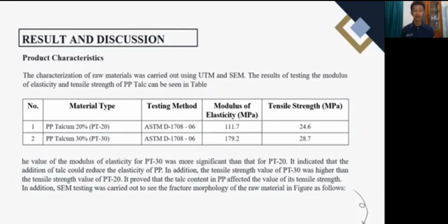You can see in the table: Number 1, material type PP talcum 20% or PT20. Testing method ASTM D-1708-06. Modulus of elasticity, MPa: 111.7. Tensile strength, MPa: 24.6. Number 2, material type PP talcum 30% or PT-30.